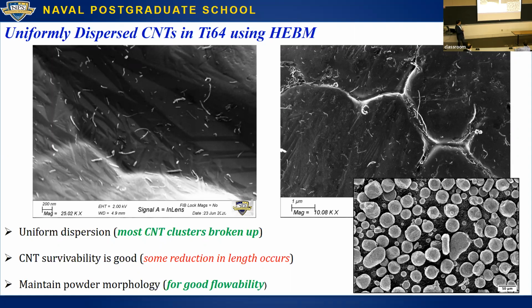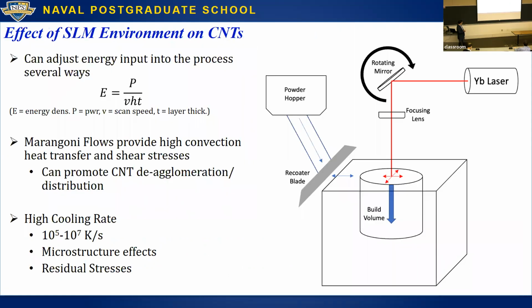CNTs are uniformly dispersed. Second goal, I said we want to keep the shape very close to spherical. As soon as you lose that spherical nature, it becomes very hard for it to flow nicely. Spheres are the easiest material to flow, and you see that here for the most part. Every now and then a particle has been a little bit flattened, but with this amount, it's perfectly fine and it flows very nicely. We needed to go through all of that powder processing just to have something that we can actually print, right? It's not a trivial process where you could just mix them. If you don't mix it right, you're going to have problems from the very beginning, like I showed with the aluminum oxide.